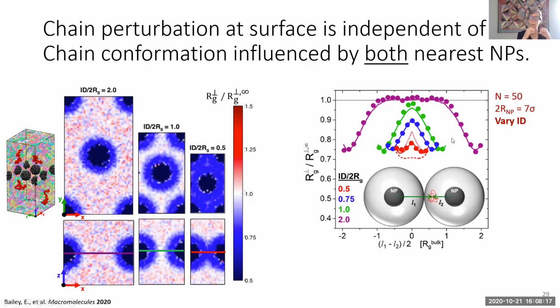And as we bring them closer together, you're getting contributions to that distortion of the chain conformations from both particles. And so if we look at the red data here, one of these curves, the dotted curve that's a little higher than the simulation data, is if the amount of distortion of the chain only depends on the particle that you're closest to. And then the dashed curve, which is below the simulation result, says that you get equal contribution from both particles. And it actually turns out to be somewhere in the middle. So that's kind of interesting.